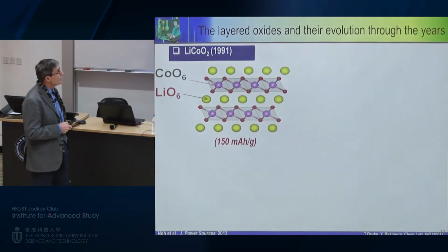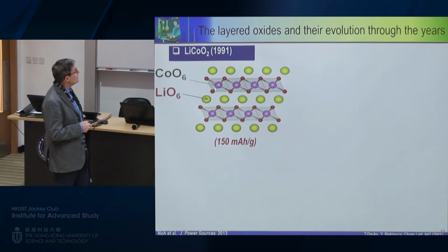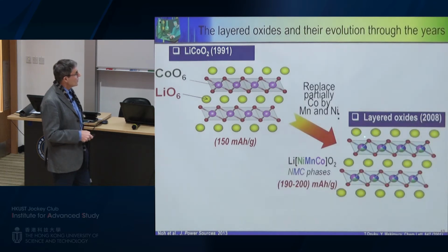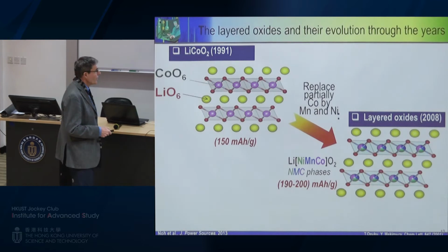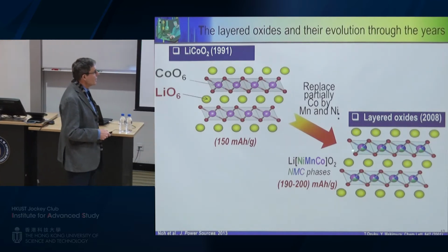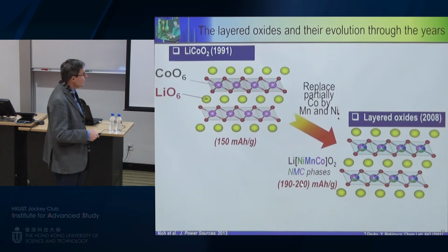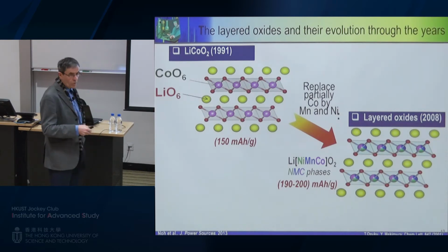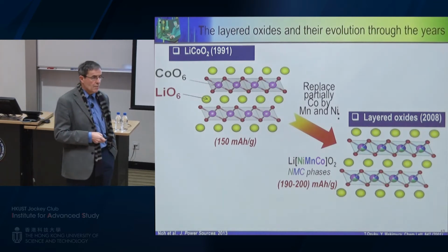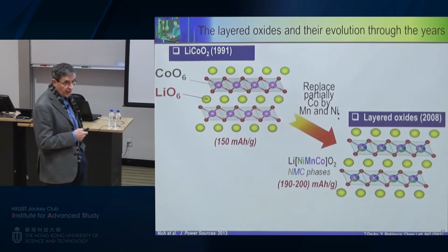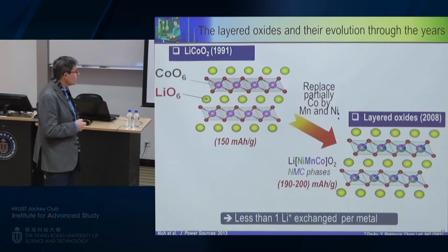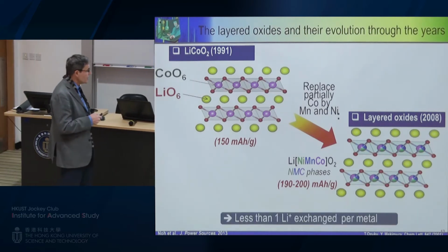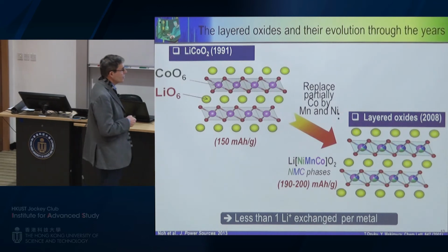So, following the progress on this layered compound, people have done some substitution within the cobalt layer. This replacement has led to this type of phase in which you replace cobalt by nickel and manganese within the metal layer. And you can see when you do this, we move from 150 mAh to about 190 to about 200 mAh. But again, the message here is whatever you are doing, you are still limited to the number of electrons that you exchange per metal.